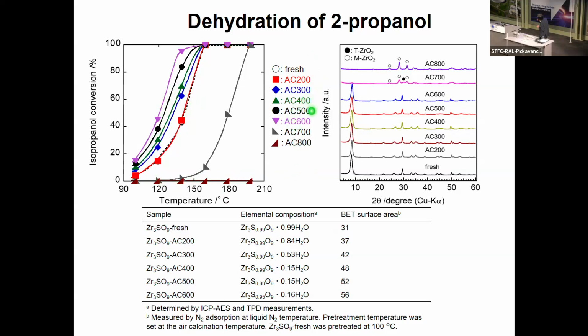After calcination at 500 degrees Celsius or 600 degrees Celsius, the structure is still the same, no change at all. And it shows higher activity, as you can see here, because the surface area is slightly increased. Why does the surface area increase? During the calcination in an inert gas atmosphere, some water remains. After the hydrothermal synthesis, some water is incorporated into the layer space. During the calcination, water comes out. By this process, the layer stacking is expanded, and then it doesn't recover to the original state. Therefore, the surface area is enhanced. The basic structure is the same, but simply the surface area increased. Therefore, the activity is so high.